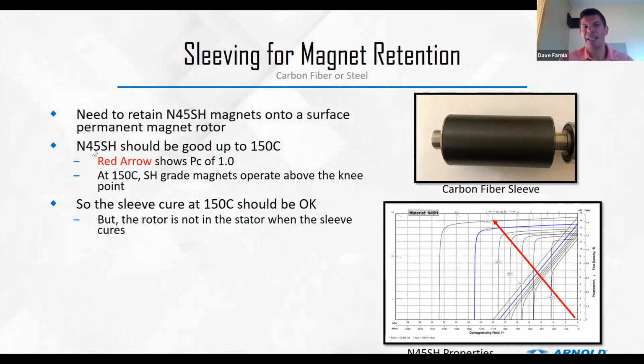So let's say we've designed our rotor and we're going to use N45SH magnets because they're good up to about 150 degrees C. So our red arrow right here on the N45SH curve, that's our permeance coefficient. A 1.0, that's phenomenal. So magnet manufacturers, we assume that you're trying to get to the maximum energy product for the magnet, so probably operating right about there. This is kind of hard to see, but that shows 120 degrees C. So it's starting just to fall off. So, okay, at 150 degrees C, you should be okay.